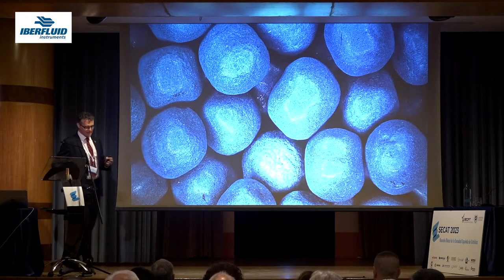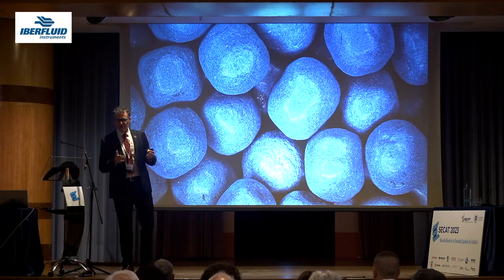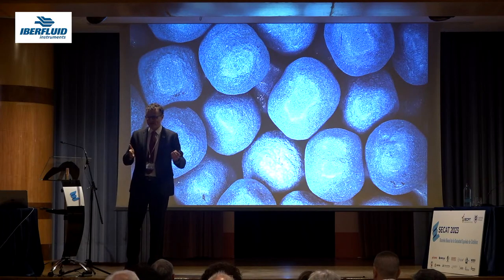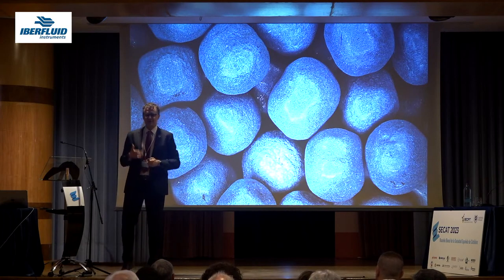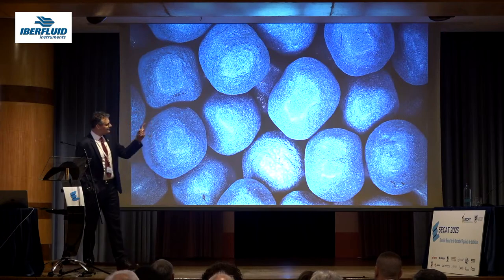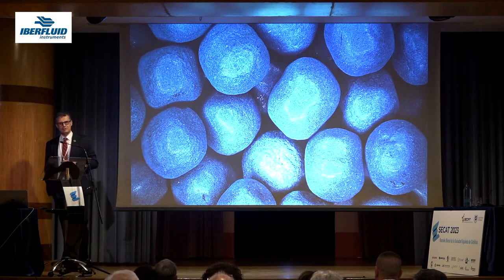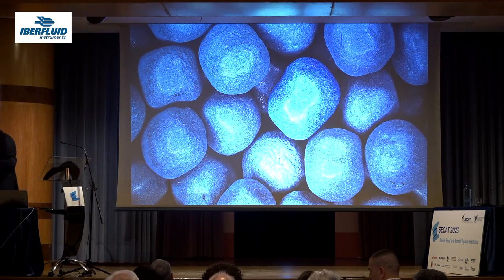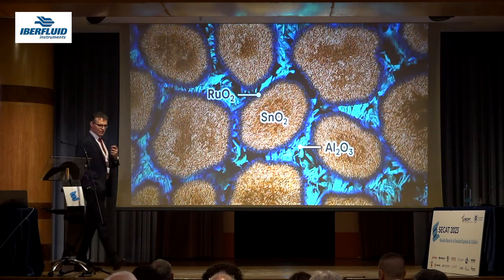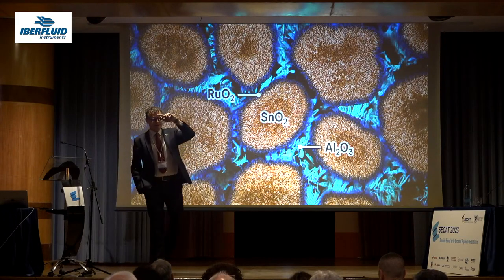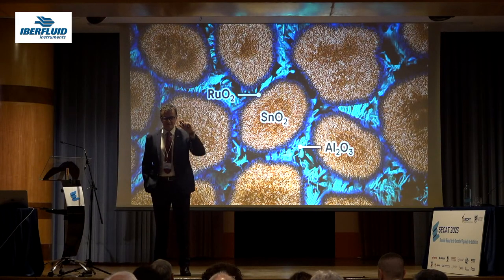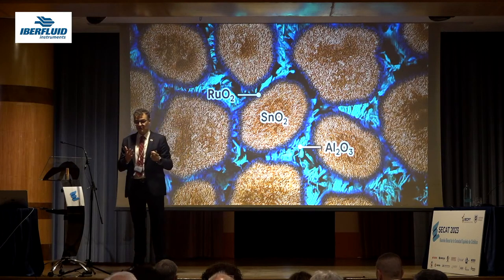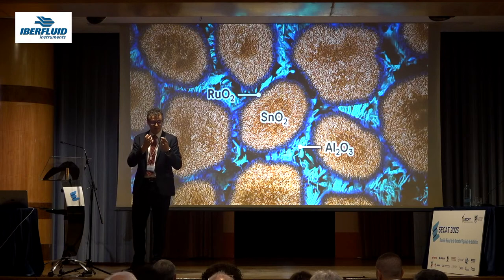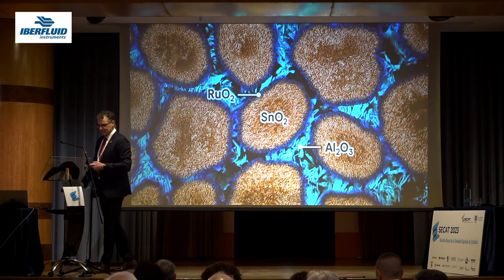A catalytic material is not just a powder. It's not a beautiful spectra, right? We need to put a catalytic material to work. And these are the granules, 2-millimeter granules of the industrial catalyst. These granules contain a very unique architecture, the architecture that I mentioned before. You have 2 layers of ruthenium oxide covering tin oxide particles. This is the support. And around these particles, you have a binder to make mechanically stable bodies. And this binder is alumina.